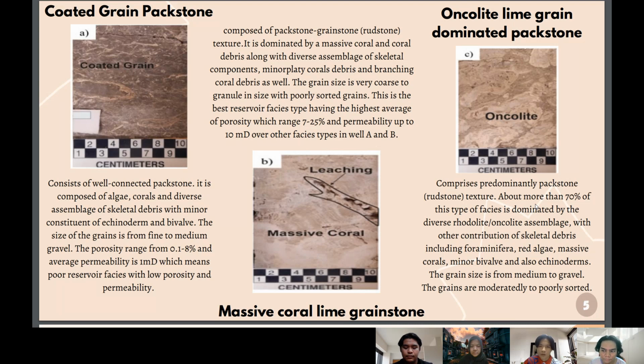The second one is massive coral limestone, the lime grainstone. This facies 2 is composed of boundstone, grainstone, rudstone texture. It is dominated by massive coral and coral debris, along with a diverse assemblage of skeletal components, monoplatic coral debris, and also branching coral debris as well. The grain size is very coarse to granule in size with poorly sorted grains. This is the best reservoir facies type, having the highest average porosity, which ranges from 7 to 25%, and permeability up to 10 md over other facies types in well A and well B.